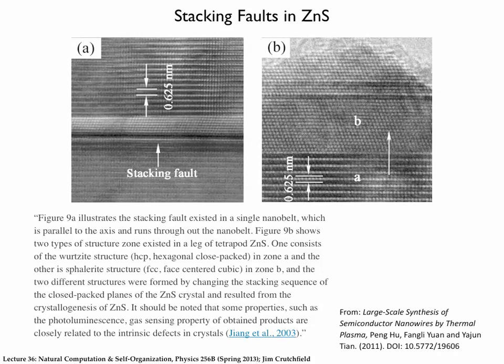Let's look at what this guy is. I apologize, it's a little bit hard to see. This is high resolution transmission electron microscopy. And what we're actually looking at is the side view, along the layers that are stacking up. Here, we see that this region, maybe easiest to see here, we have basically two kinds of layers, the bright and then the dark that's hard to see. This is period two. This is 2H structure. This is a 2H crystal. This is a little piece of 2H. Underneath it, it's hard to see here, but underneath it, it also looks to be the same. So we have a little piece of crystal here that's 2H.